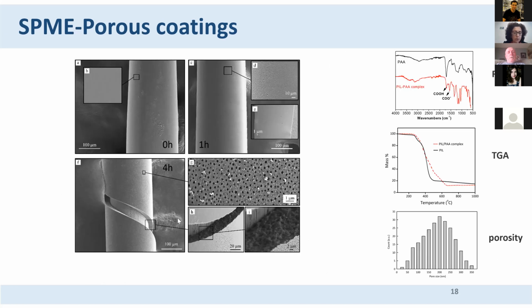So let me show you here some of the details. So here it's the fiber after coating. After 1 hour of immersion, nothing happened. We can see that it's starting to scratch there, but still the porosity is not good enough. And then after 4 hours, we have this fiber here that, yes, it is porous. And here you can see that it is 20 microns of thickness. This fiber is around 200 microns. And you can see here what I was talking about, the deprotonation of the carboxylic acid of the polyacrylic acid.